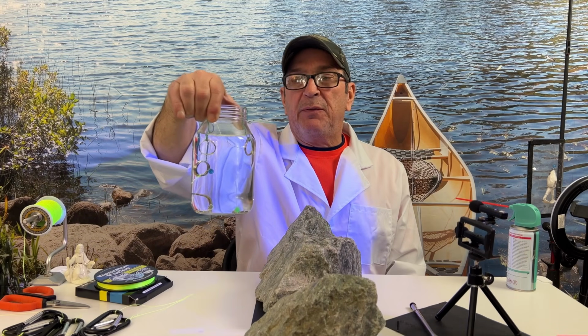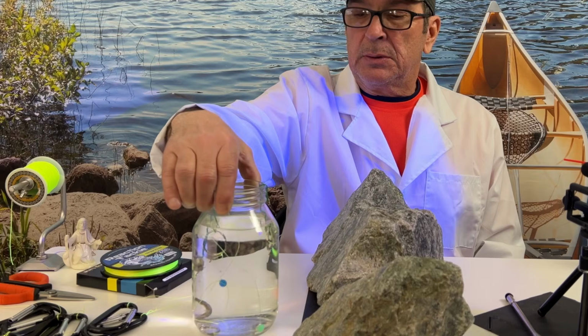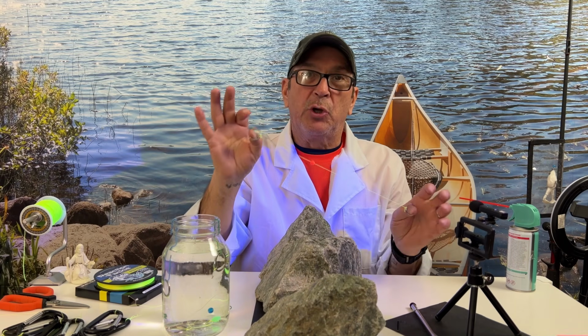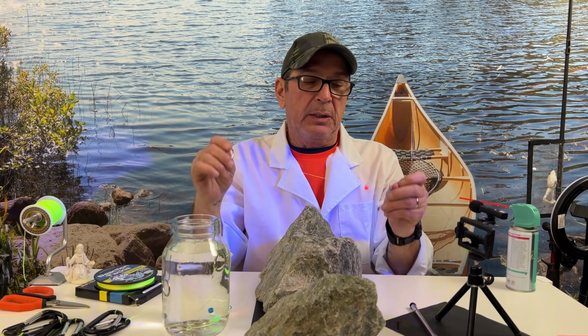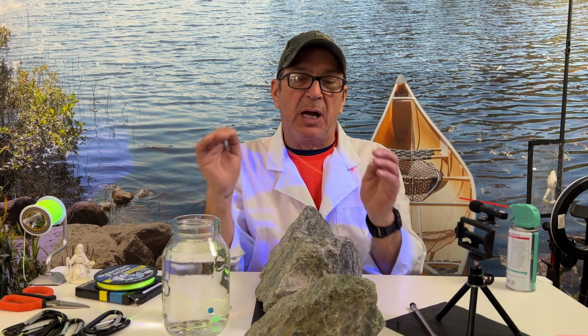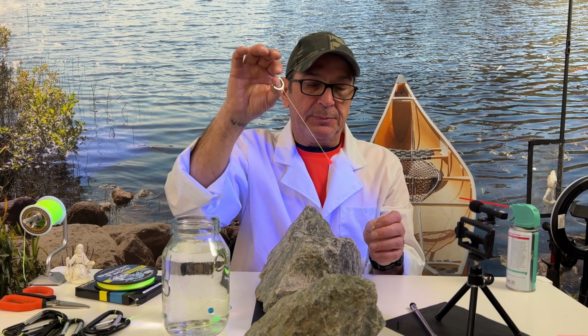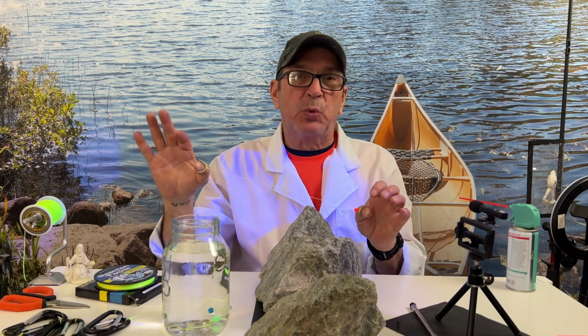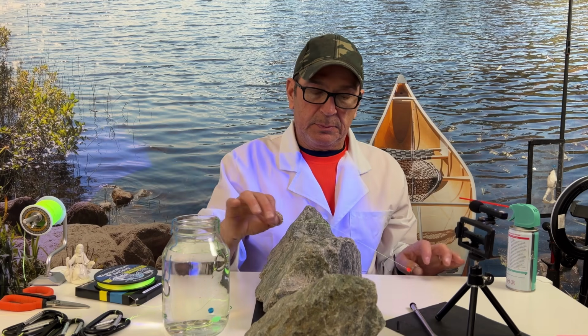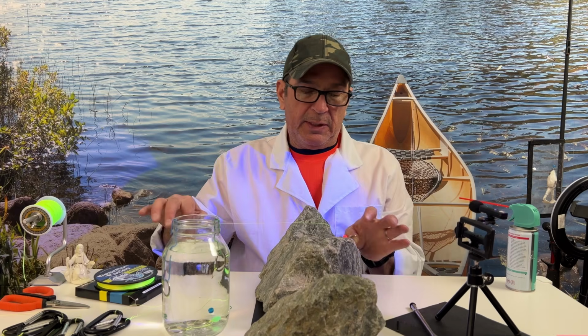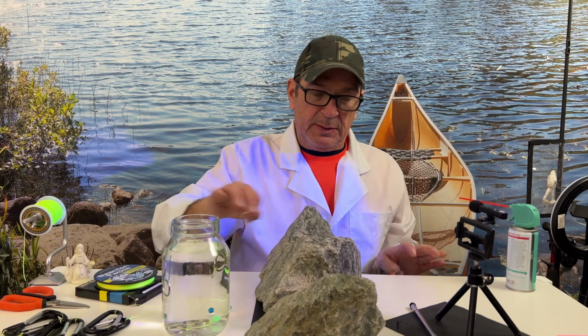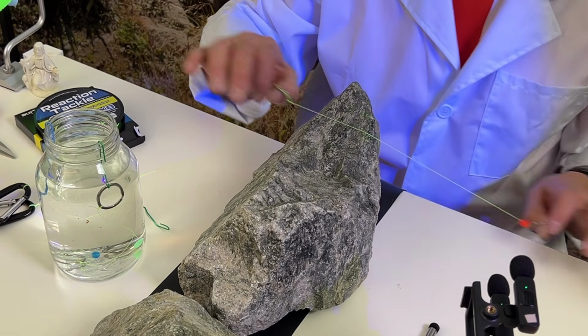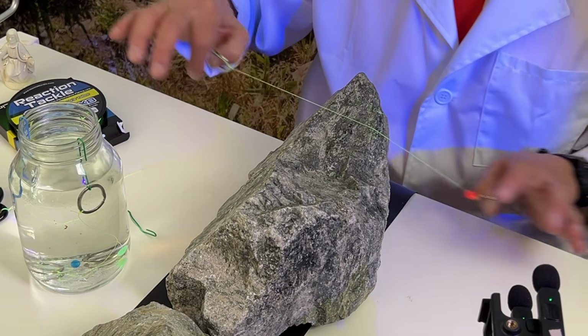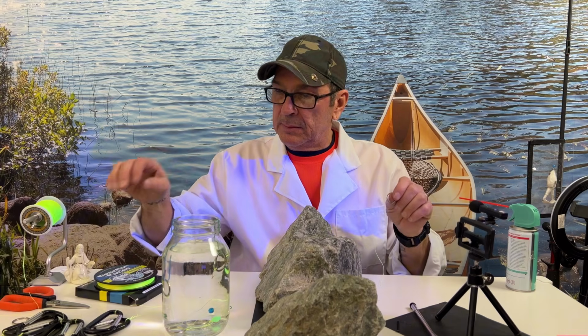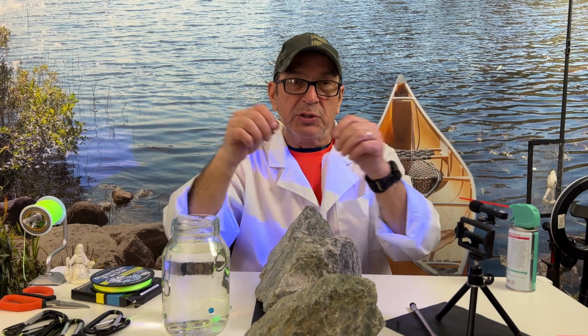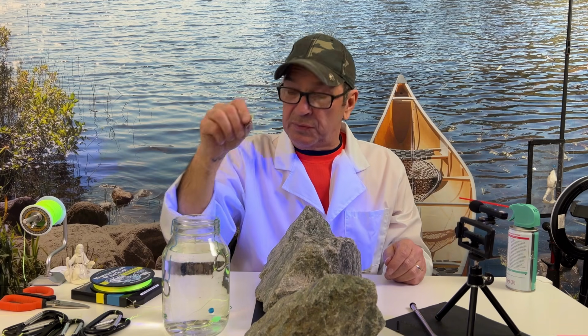Now we're going to test the wet braided fishing line that's been soaking for over 2 hours. Okay, as always, we tested orange, green, blue. This is test 1 of the wet braided fishing line abrasion resistant test. Down and up is 1 cycle. 1, 2, 3, 4, 5. 5 cycles on the first test of the wet braided fishing line. 5 cycles is very good.